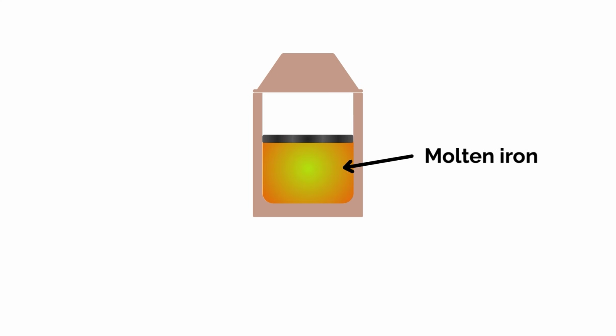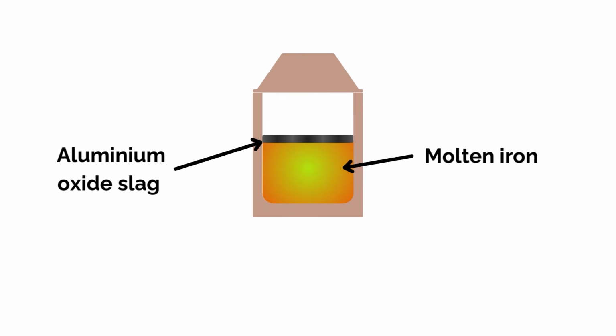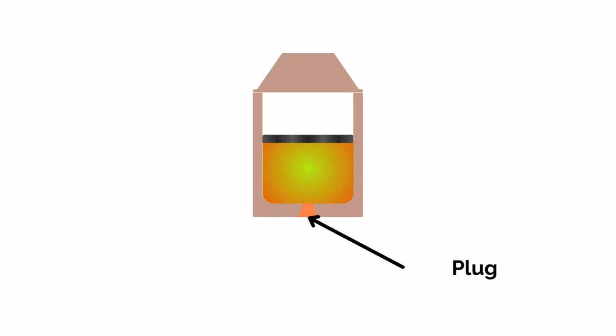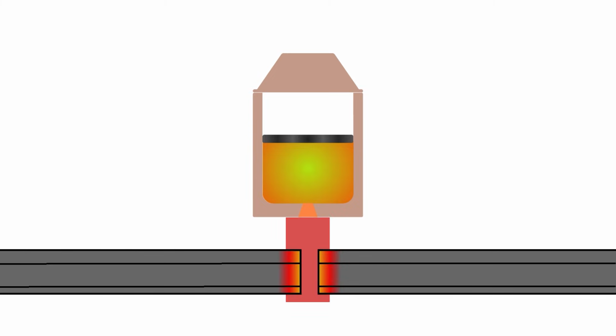Inside the crucible, two layers form. Molten iron sinks to the bottom. Aluminium oxide slag forms on the top. At the base of the crucible is a refractory plug, a heat-resistant barrier called the thimble in some systems that delays the pour. When the reaction reaches full temperature, the plug softens and melts, allowing the molten iron to drop down through the runner into the mould and between the preheated rails.